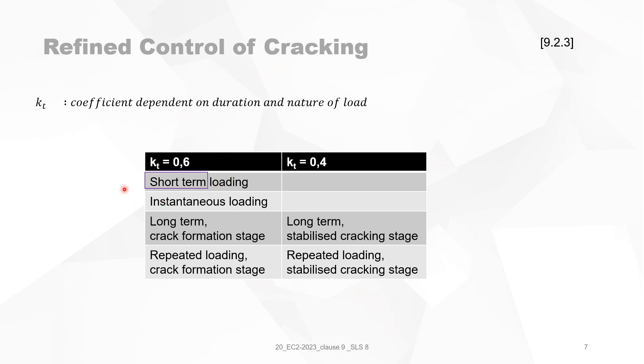The strong proposal is to use KT = 0.6 for short-term loading and KT = 0.4 for long-term situations, and to accept that in long-term cases you are always in the stabilized cracking stage. If you know from other calculations that you are in the crack formation stage, then switch from 0.4 to 0.6. But in normal cases, use short-term 0.6 and long-term 0.4.